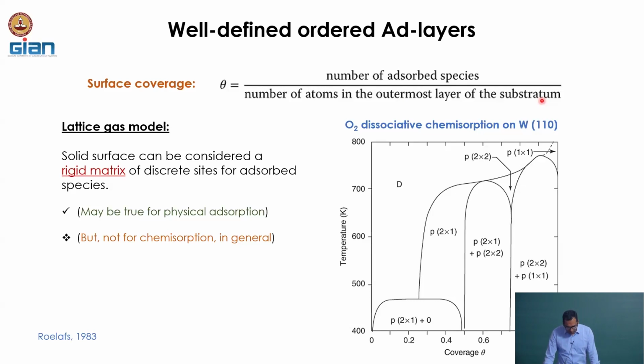Okay. And here is one example of dissociative chemisorption of oxygen on a tungsten 110 surface. What we are seeing is that when we change the temperature as well as the surface coverage, which varies between 0 and 1, where 0 means all the sites are empty and 1 means all the sites are taken up by the gas, different arrangements of the oxygen atoms are present on the surface. It can be a p(2x1) type of mesh, it can be a p(2x1) and p(2x2) combination, or it can be a disordered phase.